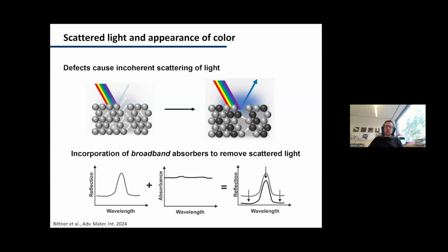In nature, this is melanin, so all animals that have structural color typically combine this with a layer of melanin, our natural pigment, which is either underneath the photonic structure or when the photonic structure is formed directly by melanin particles. And in our case, we can either use synthetic melanin, polydopamine, or we can add carbon black to simply remove the stray light.